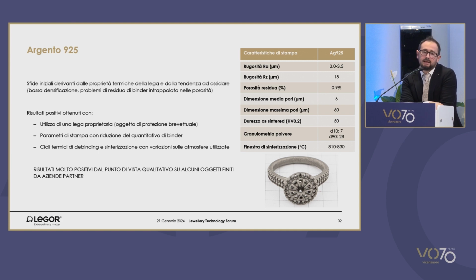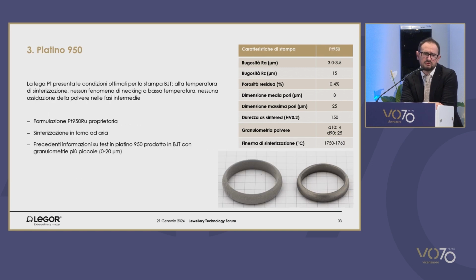And final residual porosity now is less than 1%. So in some cases, the result is much better than the 0.9 of residual porosity, but it still depends on the morphology of the item. So we still have to work on this alloy. We still have to fine-tune it to be able to say, yes, it perfectly meets the needs of the jewelry industry.